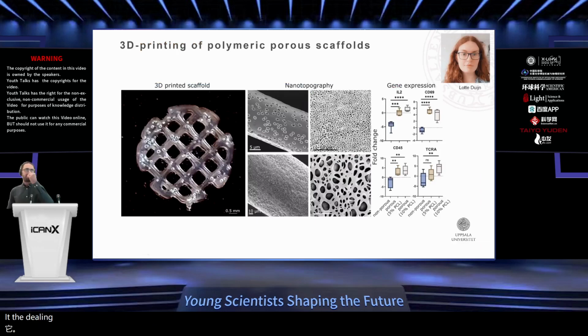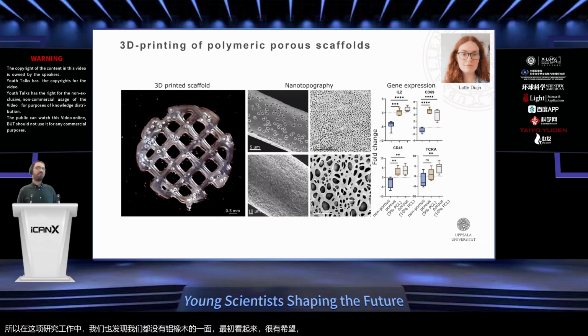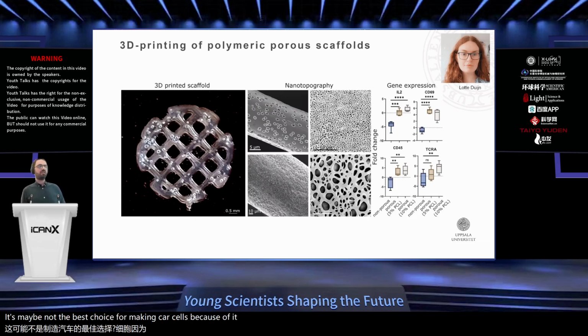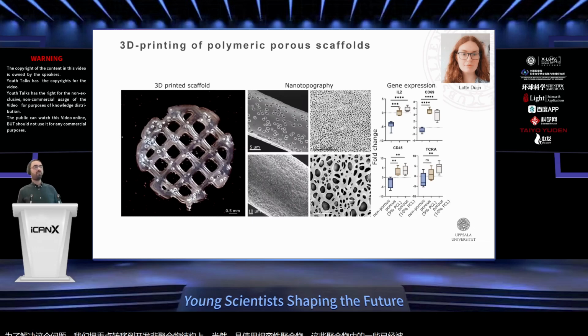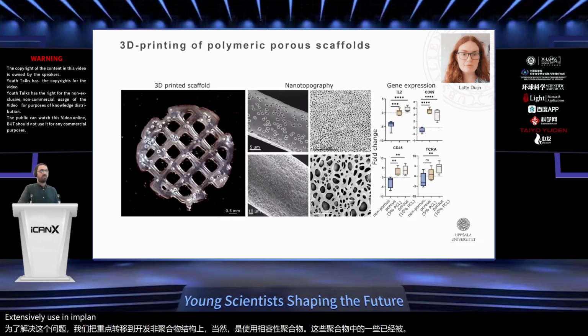So during this research work, we also found that nanoporous aluminum oxide, which initially seemed to be quite promising, may not be the best choice for making CAR T cells because of its mild toxicity. And to address this concern, we shifted our focus to developing nanoporous polymer structures using biocompatible polymers. Some of these polymers, for example, have been extensively used as biodegradable implants and show excellent biocompatibility with cells. And we wanted to make sure that they don't harm the body.